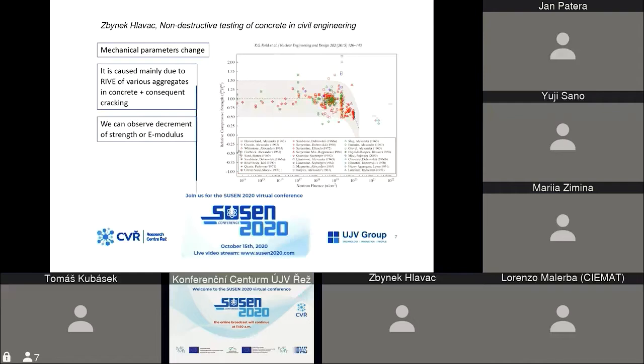So on the right-hand side picture, you can see what happens if a lot of neutrons come through 1 square centimeter. During about 30 years of operation of a nuclear power plant, you reach 10^19 neutrons per square centimeter, and within this number, the mean value of all the compressive strength tests is about 1. It means that the test before irradiation and after irradiation is equal to 1. It's 100%. Nothing happens, plus minus.